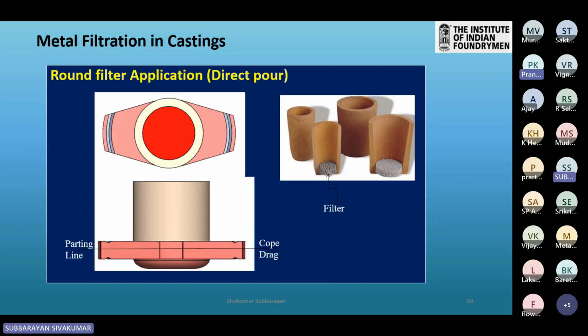It is a typical round filter application in many machine molding lines. It is being used as a direct pour method, particularly for wheel type castings, a single pour at the center with minor ingates, or directly over the casting. It is being successfully implemented with a high level of yield. The only thing, we have to ensure that the filter floats when the pouring is over. Otherwise, it will create a choke in the neck, and it may affect the riser effectiveness or riser efficiency.